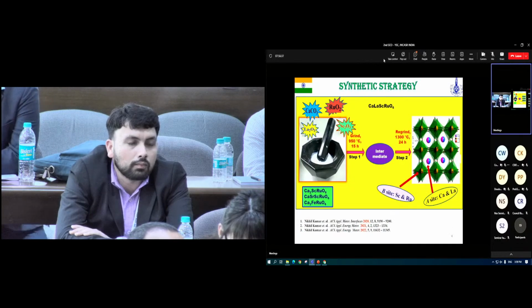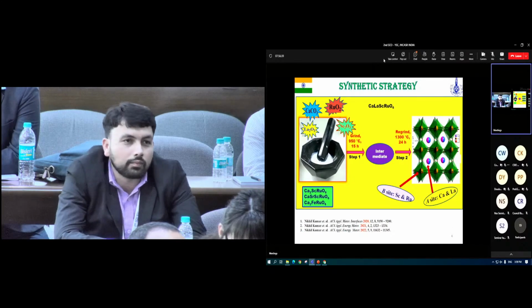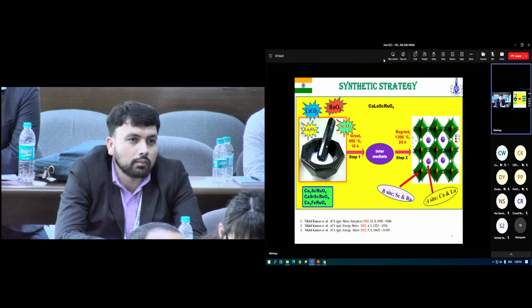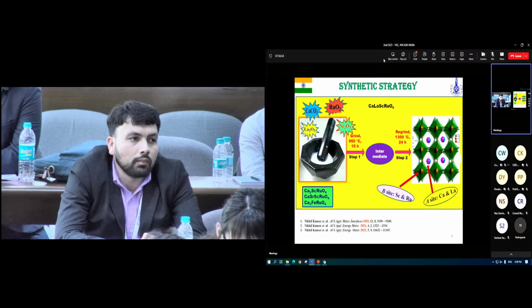We have used solid state reaction to synthesize these perovskite materials. For example, in our lab, we have developed this material, calcium lanthanum scandium ruthenium oxide, which is a double perovskite where calcium and lanthanum are at the A site and scandium and ruthenium at the B site. Here we have used carbonates and basic metal oxides and ground them for 1 to 2 hours, and then kept them at high temperature for 15 hours, with intermediate regrinding, and again kept them at 1300 degrees for 24 hours, and we got this CLSR pure phase material.